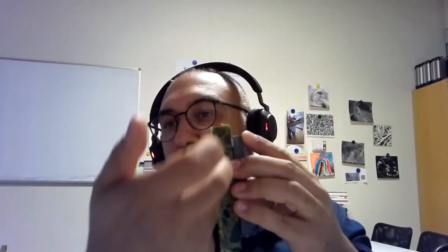So if it's a really thick sample and you're interested in cutting or examining the middle part, it doesn't make sense to impregnate from outside and then cut and look and see the crack. That is not possible. If you want to do that, one option could be to cut your sample not at the surface you're interested in, but a little bit thicker, impregnate, and then try to grind it down. That could be one option.